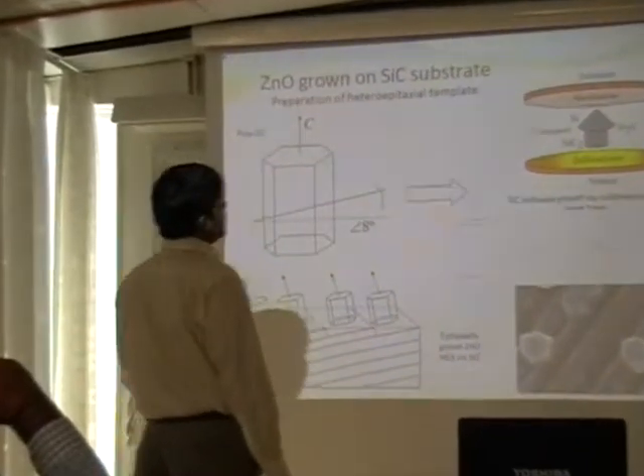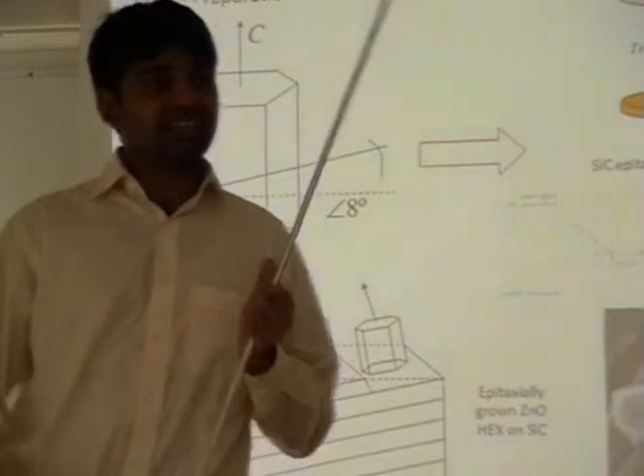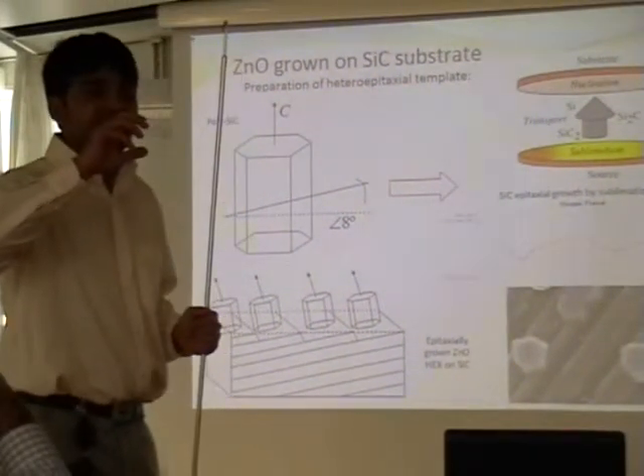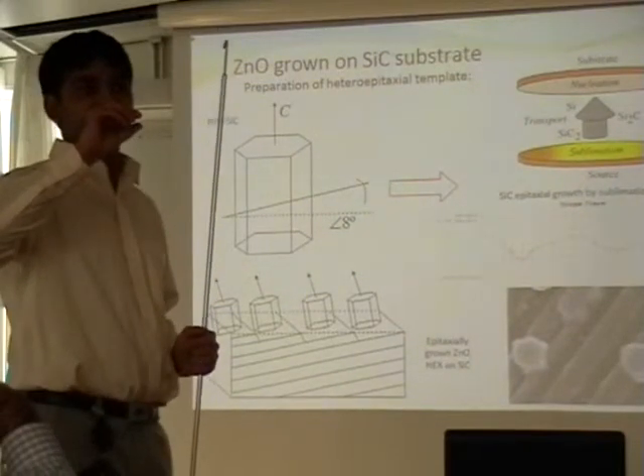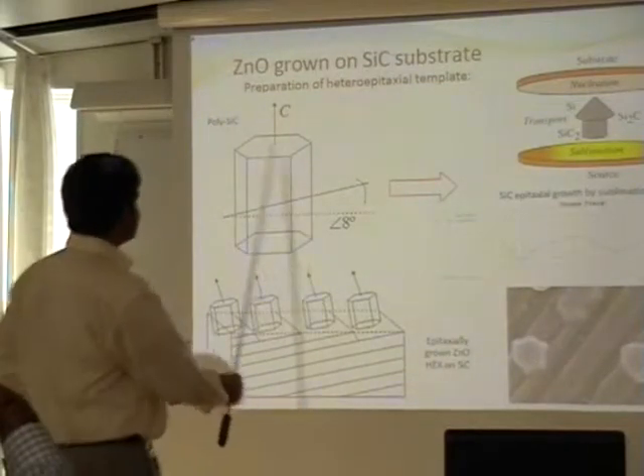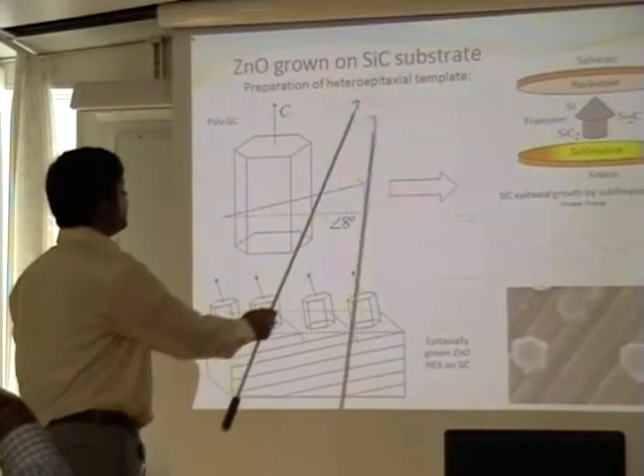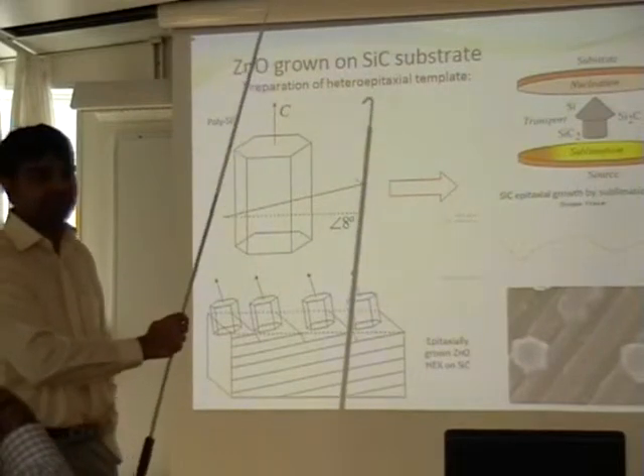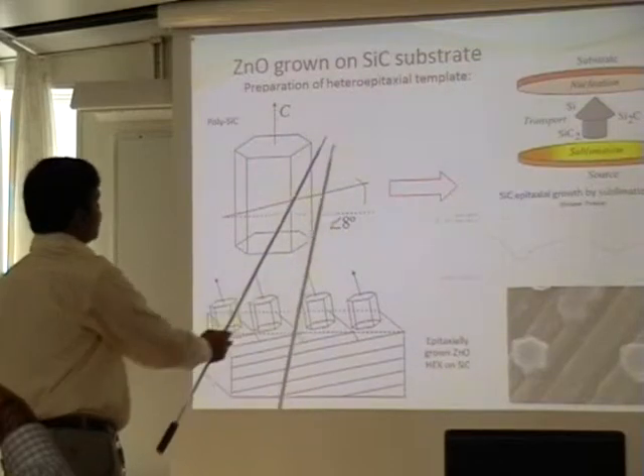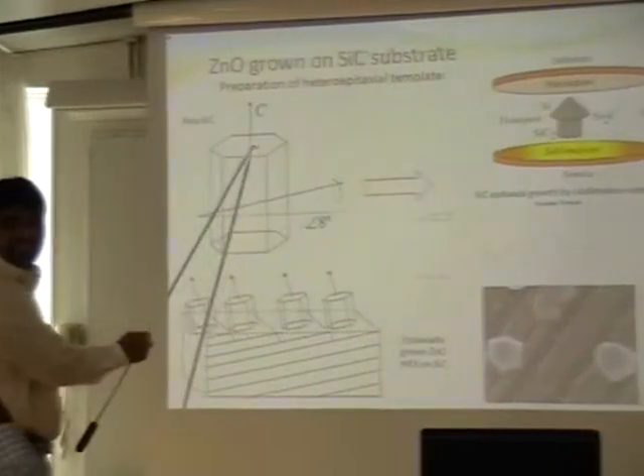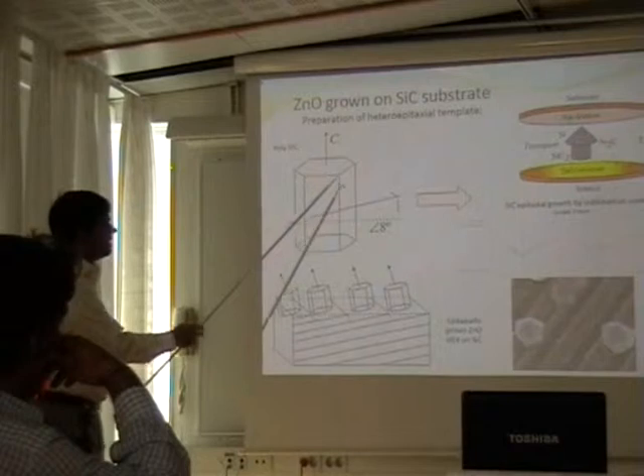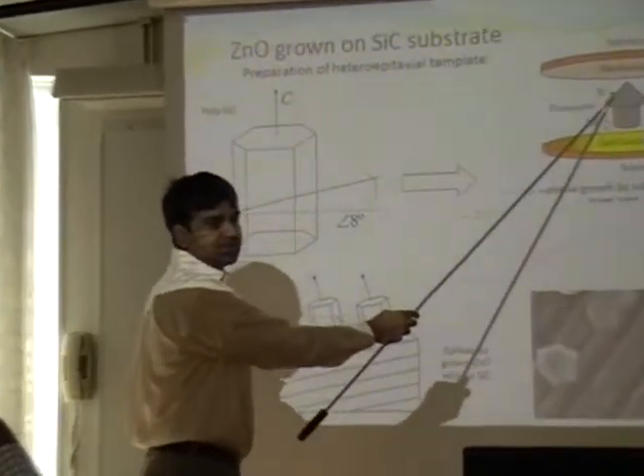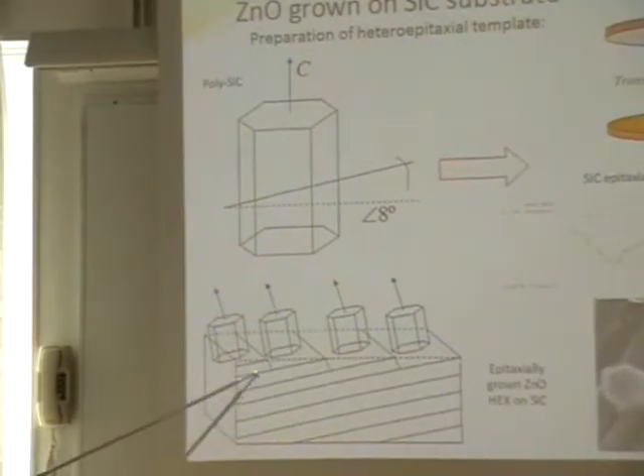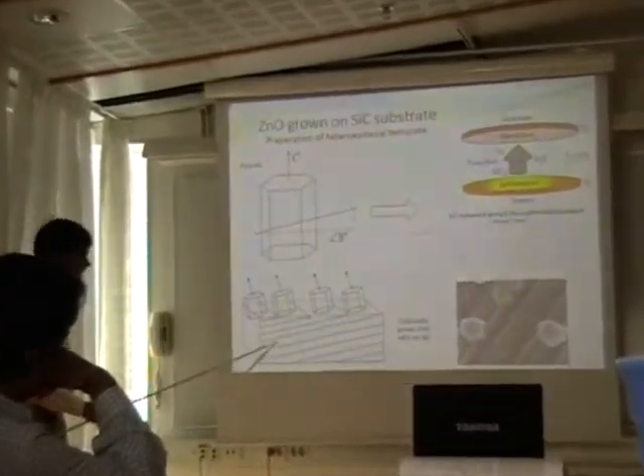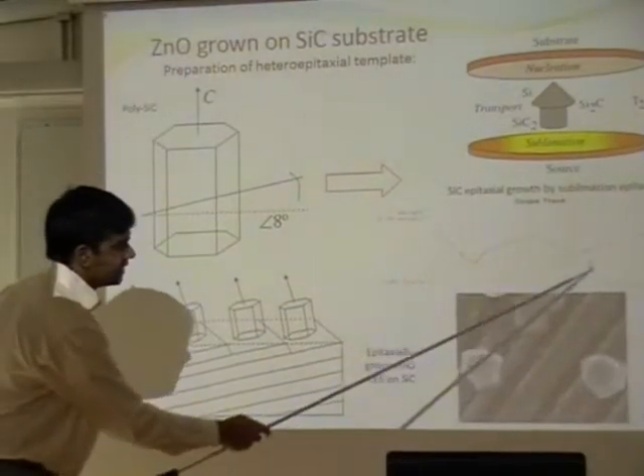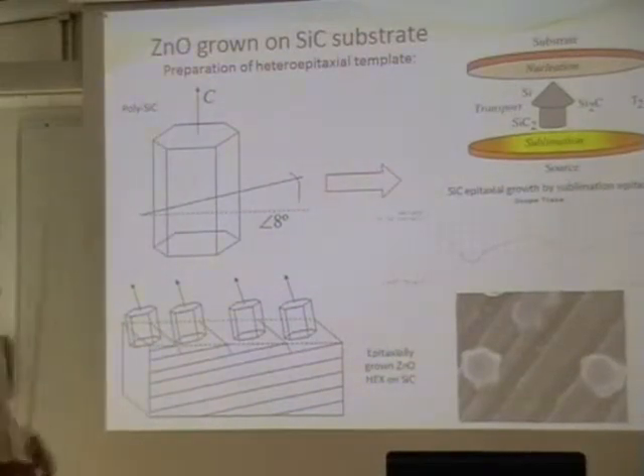Here, zinc oxide on a silicon carbide substrate. In the second section I told you, we got an idea, the sample has been grown on a homoepitaxy substrate, but it didn't give a good result. This time, zinc oxide was grown on a silicon substrate through heteroepitaxy. In this heteroepitaxy template, first silicon was cut by 8 degrees, silicon carbide was cut by 8 degrees, then again grown on silicon through the sublimation process. It is like this plane. They are cut by 8 degrees. Here you can also see from the AFM picture, and through SEM they show a hexagonal shape.